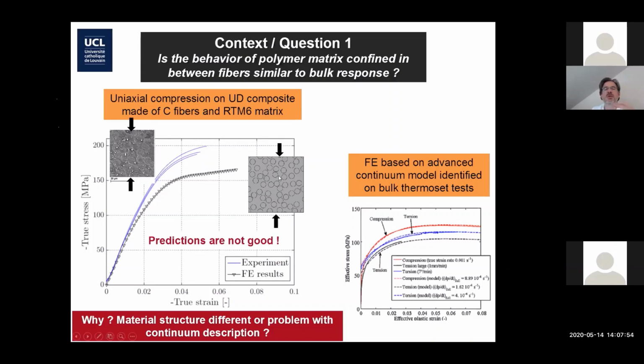Fibers, we know what to put. It's a UD on the compression. It's an easy problem. And this is the best we can get. So our predictions are 15 to 20% below the experimental data. And we have not put any damage. Huh? If we would put damage, things would be worse. The curve would be even lower. And we do see damage experimentally. So, and we tried many things, and honestly, the only conclusion we can get is that the behavior we put for the matrix is not correctly describing what's going on.